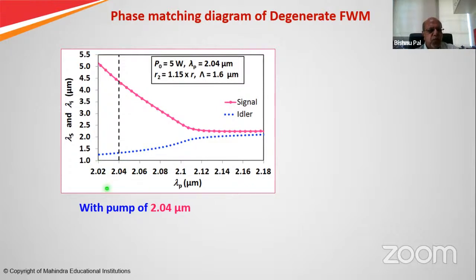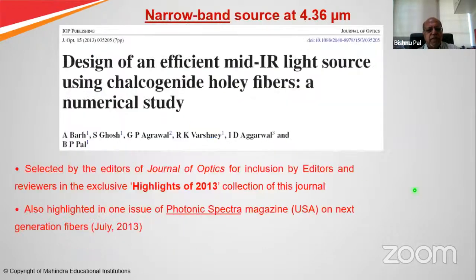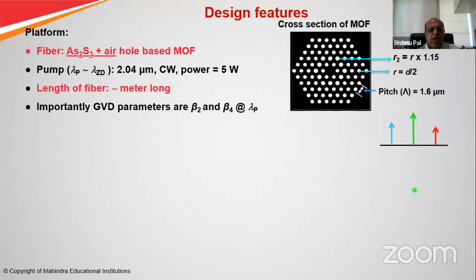And 2.04 is also a wavelength where thulium doped fiber lasers emit. So they are commercially available and high power is available. So we designed such a mid-IR wavelength source from a nonlinear fiber, in which we used a thulium doped fiber laser as the pump, and the signal comes out at around 4.36 micrometer. And it is a narrowband source at that wavelength.